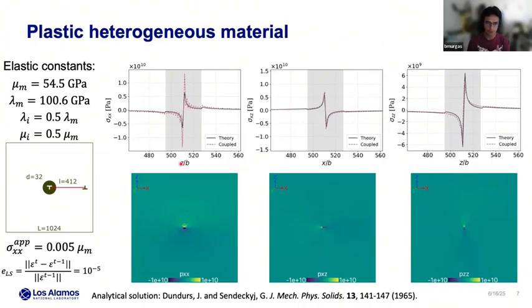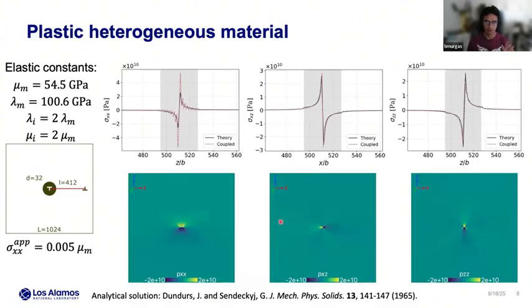You may notice that we have some oscillations. This is because we are using FFT solvers, and this is inherent to FFT solvers. Then I did the same for the harder inclusion, and the solution fits pretty well to the analytical solutions. I did softer and harder inclusions because we had a limitation in the virtual strain formulation for the harder inclusion case. So we wanted to make sure that it worked for both cases, and we overcame the difficulty of the previous formulation. That was a really nice thing, to be sure that it's working well.